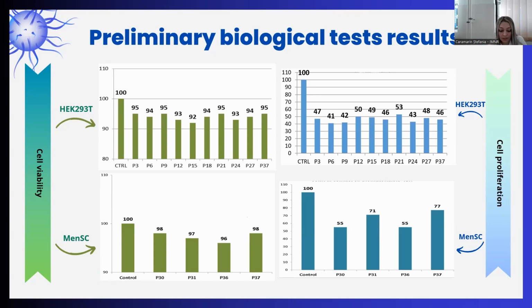Regarding the cell proliferation, things are a little different. As you can see on the right side of the screen, the proliferation of the HEK cells cultured in the medium that was in contact with our biomaterial varies between 41 and 53%, indicating that the proliferation of this kind of cells is affected by the presence of our biomaterial. But in the case of MenSC cells, you can see that the results are a little better. Proliferation varies between 55 and 77%, with an average value of 64%, higher than the average value for the HEK lines.